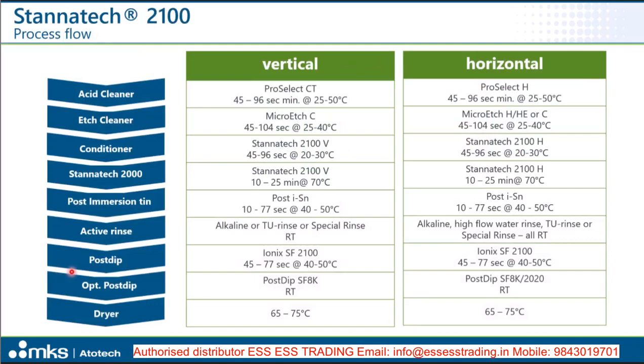In terms of process flow, it can be applied in vertical as well as in horizontal mode. Actually, from the micro etch step on, the process is comparable. We have a cold conditioner step similar to our Stannatech 2000, followed by the active immersion tin plating step, and then post-treatment, which is a post-immersion tin step, a diluted immersion tin pass to reduce the drag-out losses of the process. This is followed by active rinse concepts, which can be either an alkaline thiourea rinse or the so-called special rinse, which I will also introduce later, followed by different post-treatment solutions, which are optional and can be applied to further improve or reduce the risk for any appearance issues of the immersion tin layer.